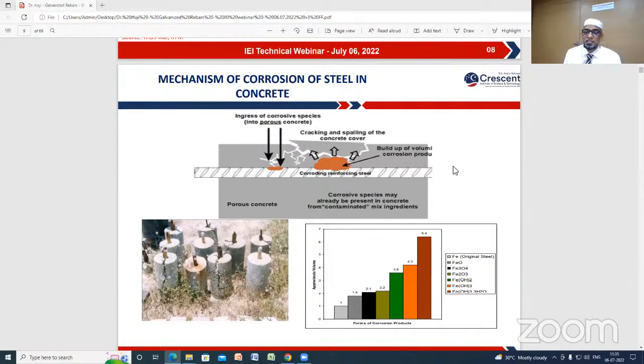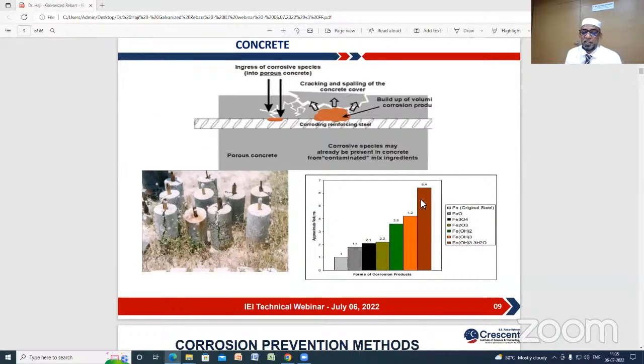We have to understand one more thing: rust in various forms can increase the volume up to 6 times the original. Suppose 10 grams of steel is involved in corrosion; there is a possibility that it grows up to 6.4 times by volume. So there is a huge deposition of corrosion product around the steel, which will give pressure. You can see this from this picture. There is a vertical crack. It is due to the volume growth by rust.